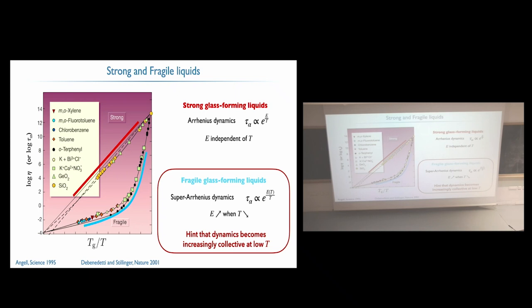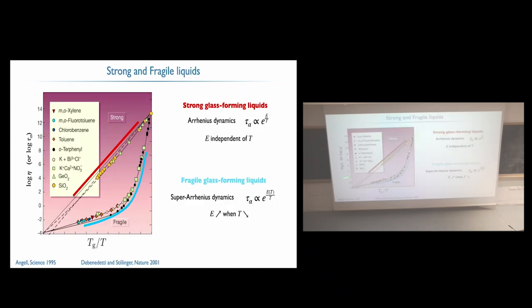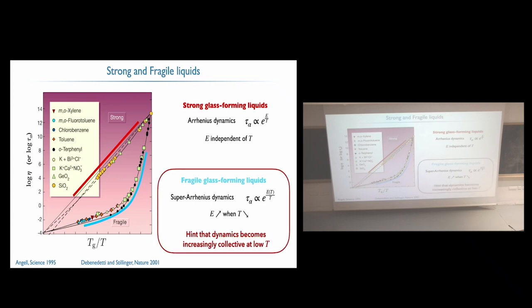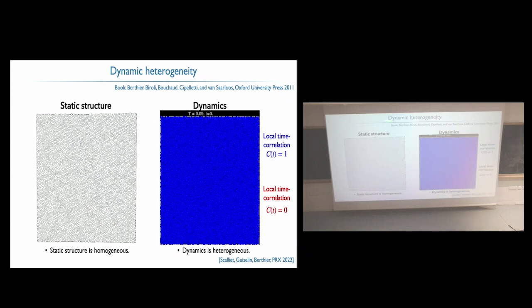Also, again, feel free if you have questions or things that you want to ask or interrupt. It's completely fine. So up to now, I've been discussing relaxation time, a bit as if there's only one time scale that dictates the behavior of the liquid. But this is really not the case, because there is something called dynamic heterogeneity, which really characterizes these very slow liquids. On the left, maybe a larger system, you see a static structure. It's a computer model. You have all the small particles. If you look from far away, you don't see any particular correlation in the statics, and the structure is really homogeneous.